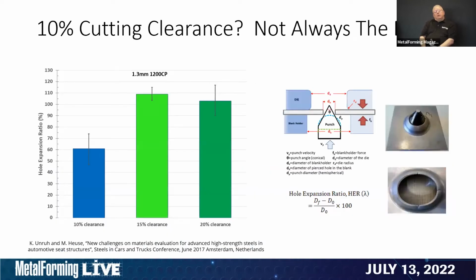And as an example, you probably have heard of the old rule of thumb, 10% clearance between the punch and the die. Well, that doesn't always apply anymore. 10% may have been great for mild steels, but for advanced high strength steels, it's not always the best. I'd mentioned the hole expansion test, and that's what the graph that's shown on the left is referencing. And if this is a complex phase steel that has 1200 megapascal tensile strength, that's around 175 KSI strength.